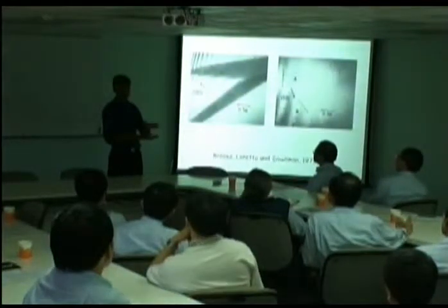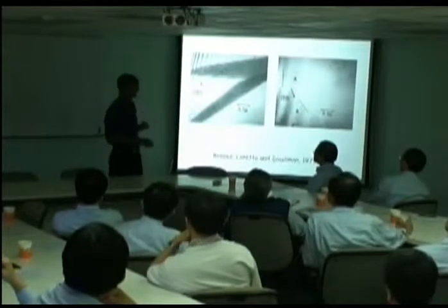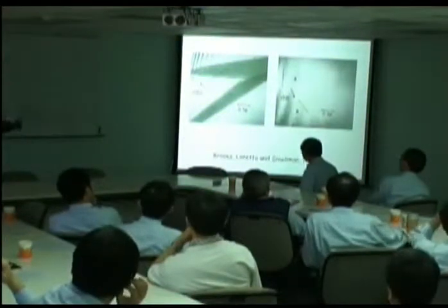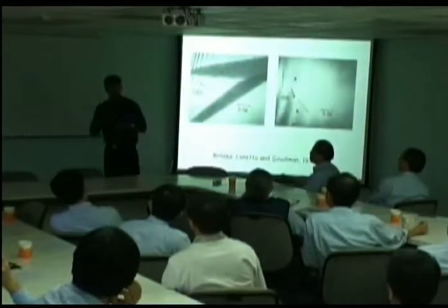So this is a really beautiful experiment by Loretto and Smallman, which is direct evidence that a single stacking fault is a nucleus. And they change the concentration of cobalt, and the volume change increases or decreases, and the contrast changes as well. So we have proof that a stacking fault is a nucleus for hexagonal close-packed iron. And of course, a stacking fault develops by a dislocation dissociating. Okay, so you have a perfect dislocation which changes into two partial dislocations. So it's a mechanism which involves the glide of dislocations, the shear deformation.